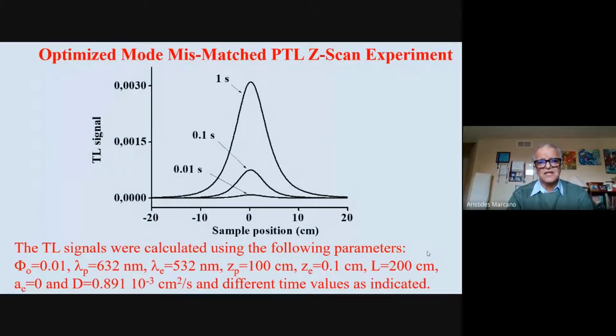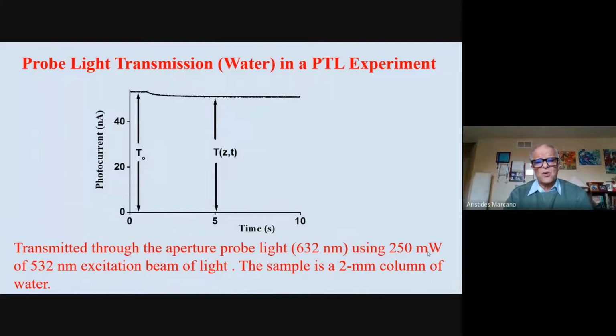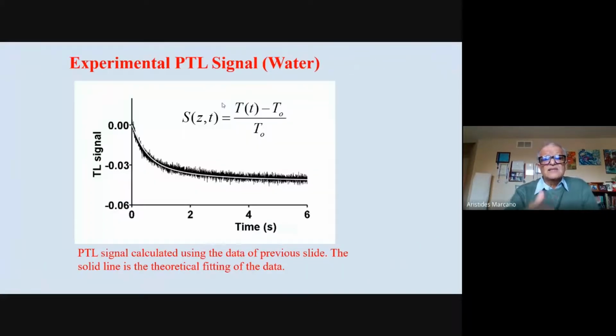Anyway, that's calculations. That's the reality. That's just a column of 2 millimeters of water, just simple, clean, distilled water, and you can see how the transmission changes in time. You are chopping your pump, and when you don't have your pump, you have this level T0. This is the level of light transmitted when you don't have the thermal lens. And that TZ is the level of transmission when you have the thermal lens. You can see that even using a small laser, even using a sample that has very low absorption, like water. And that's the real signal we calculated.